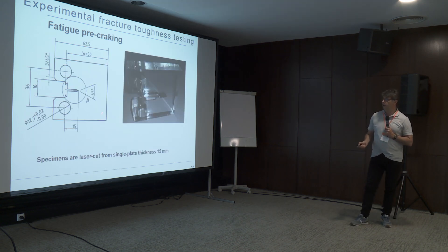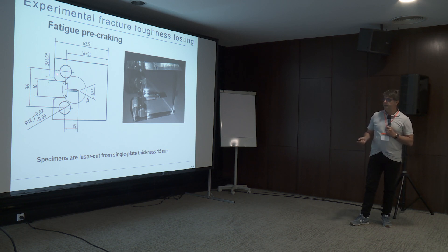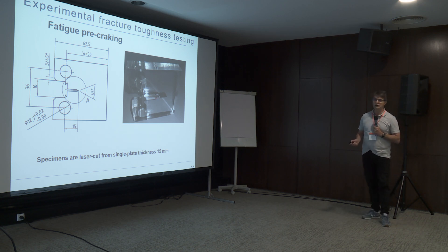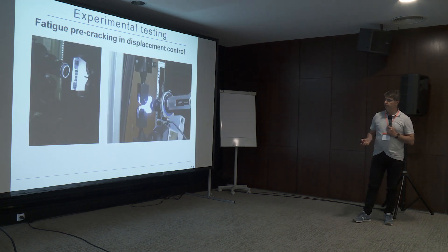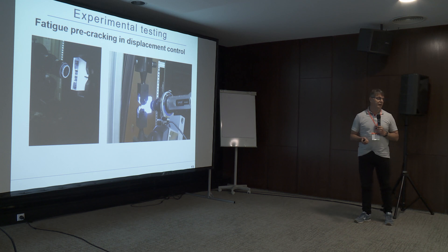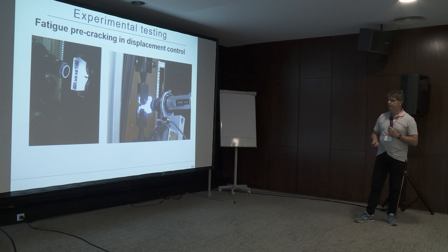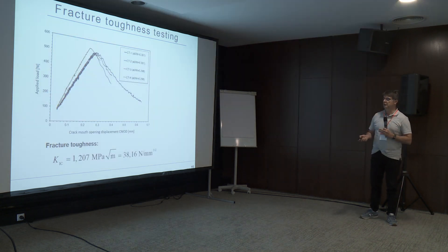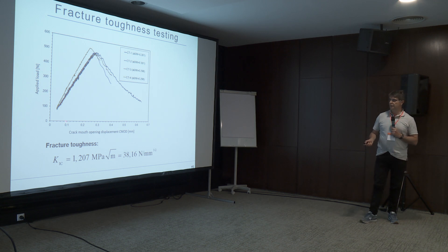Our specimen is similar to the standard specimen but with a thickness of only 15 millimeters. We also have the crack — we made a fatigue pre-crack. But of course, this material is so brittle that you can do it only in displacement control. Otherwise, in load control, the crack will immediately cause failure. We can see how the crack starts in the middle and then grows. After fatigue pre-cracking, we performed fracture toughness tests on these specimens.